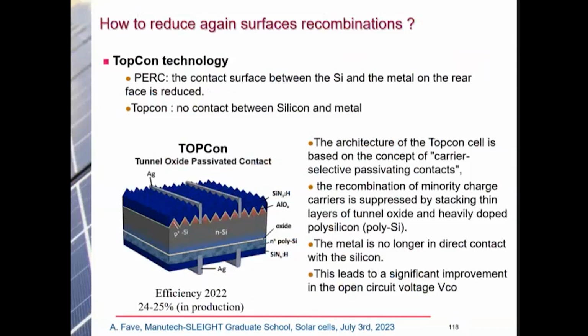The choice of this oxide: there are many kinds of oxides that can be used. The standard one is silicon oxide, but you also have aluminum oxide, titanium oxide, nickel oxide, and so on. Many possibilities. The choice of the oxide will depend on the type of material you have, whether it's P-type or N-type. It will depend on the maximum temperature you want to use,